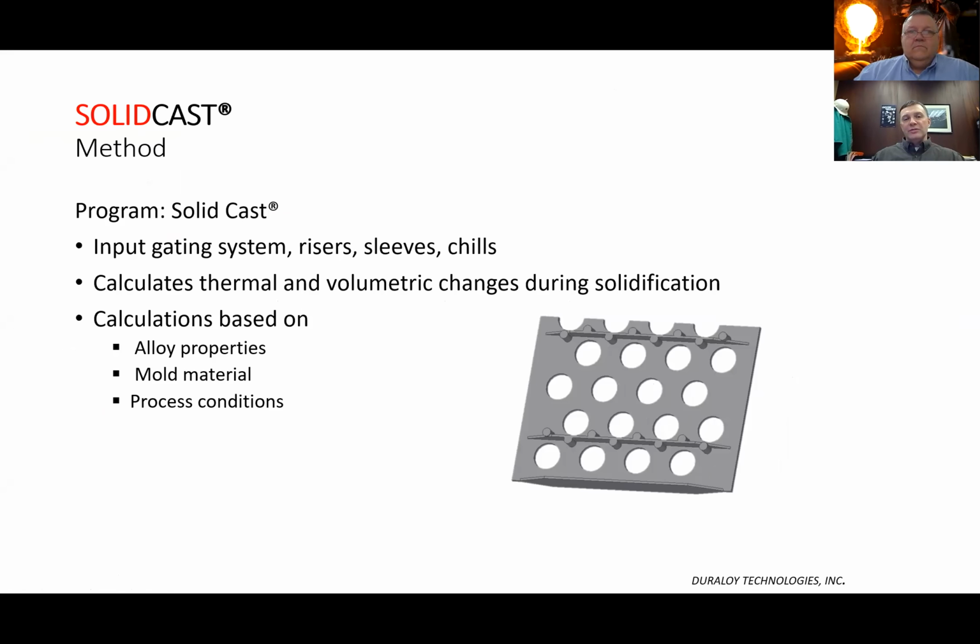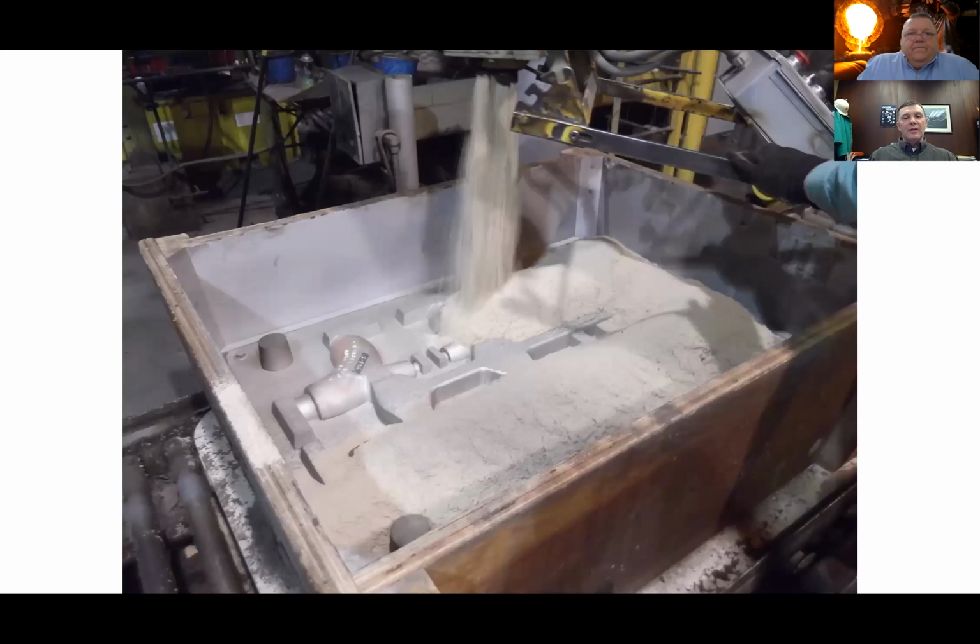What the solidification modeling software helps us with is the box or the casting size, like the taper and the head size and everything like that. So it optimizes the yield of the casting. That way we don't have to always make a sample casting. We can run things through the model, see what the head size comes out to be, see how many pieces per mold we can get, what tapers we need. And it allows us to process things through a little more quickly and not have to wait on the sample castings process through. Go ahead on to the next one then.